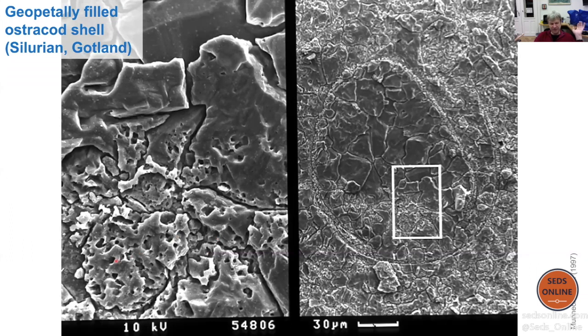So probably there was just aragonite needles, fluffy aragonite needle mud inside the ostracode and water above. And when cementation started, the crystals growing here in the lower part, they incorporated the needles. The ones on top were massive. And some crystals like this one are basically a typical calcite spar here in the upper part and a pitted microspar here in the lower part.